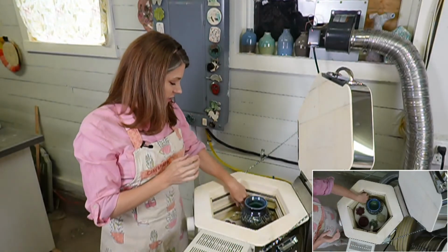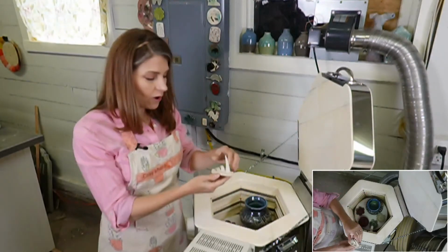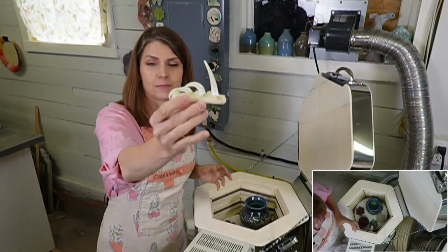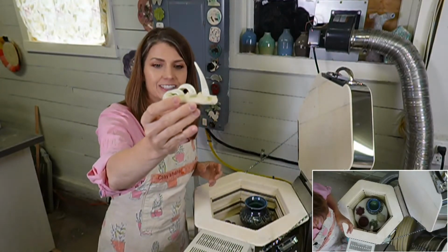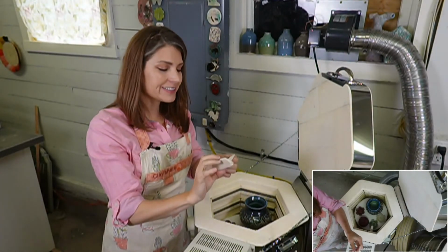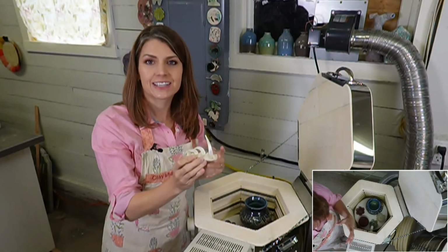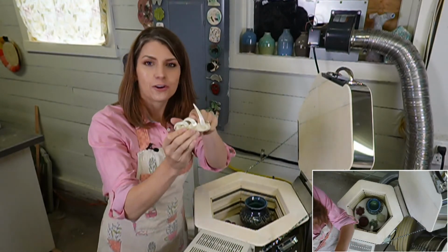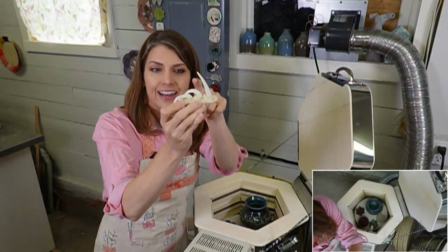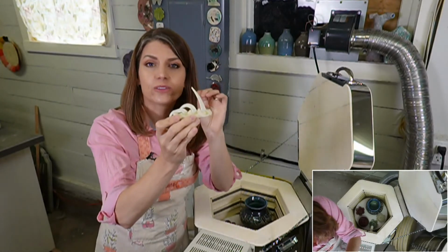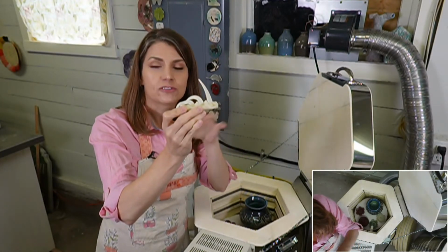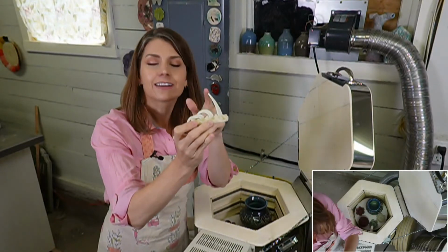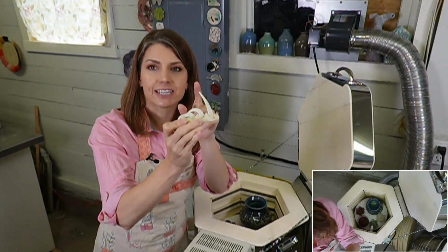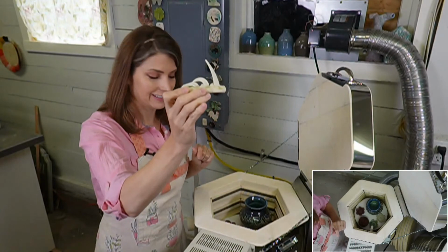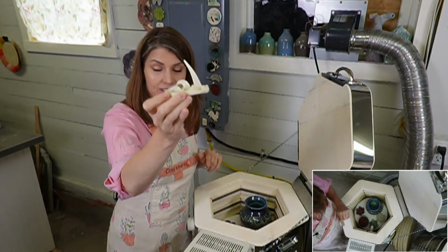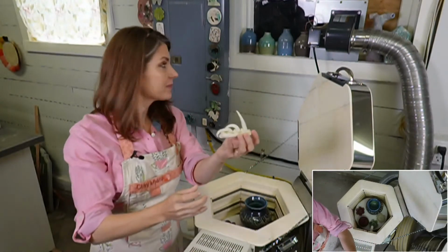So let's just take a look at the cone pack. I don't always use a cone pack with such a small little kiln. You don't necessarily need to, but it's nice to know when you're doing a test for a glaze that cone 5, which is right here, that I achieved cone 5, so I know that the kiln got to temperature. So if there's any problems in here, it's not going to be due to the kiln not getting to temperature. So that's very important. So that's my cone pack.